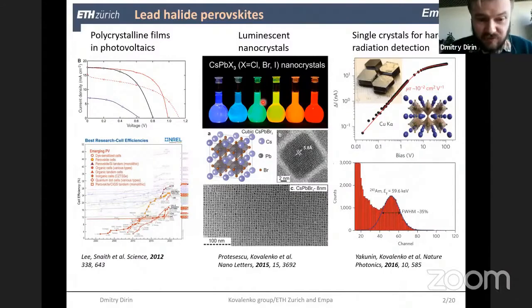So in 2015, the group of Professor Maxim Kovalenko proposed a synthesis of nanocrystals of these compounds, namely cesium lead halides in this case. And we have shown that those nanocrystals can be very bright without any additional treatment and without shelling, which is quite unusual for colloidal semiconductor nanoparticles, as I will discuss in the next slide.